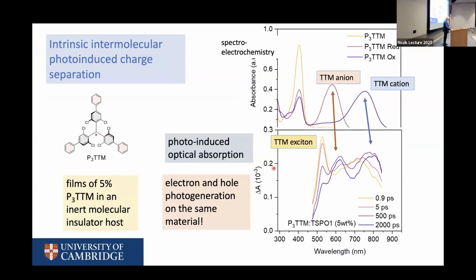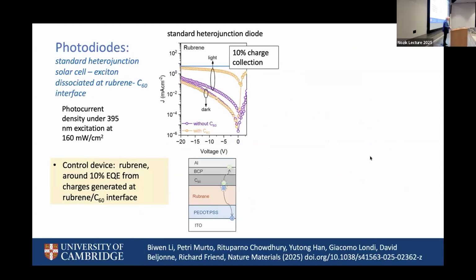So now we're going to photoexcite, absorb photons. And what we start off with is an absorption associated with the initial excitons. And then as time goes by, we see the appearance of the anion and the cation. You see an optical signature. We've got both charges intrinsically photogenerated. And if that were to work, we ought to be able to extract charges in a solar cell.